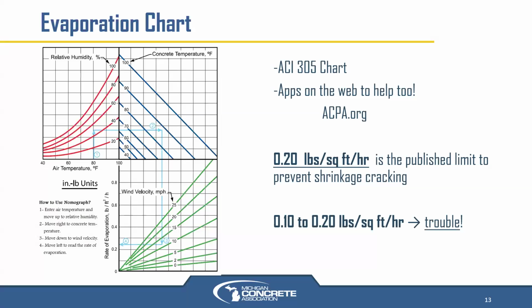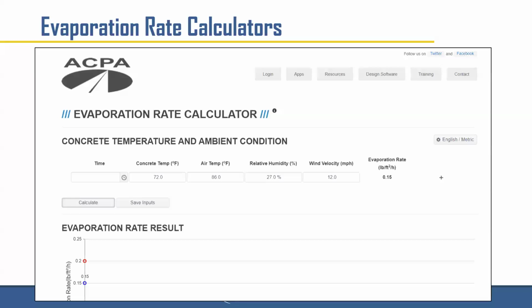Now, I say that in air quotes that you can't see, because you still need to cure your concrete in all situations and most specifications require it. And every issue that I see where there's a surface issue, typically no curing or lack of curing was the issue going on. So we'll go into that. But if you were to use the nomograph, 0.2, that's the red line, but I find that 0.1 is actually more of a critical number. Here's a screenshot from that ACPA website. You just plug in your temps, your humidity, and your wind speed. It'll spit out your evaporation rates.